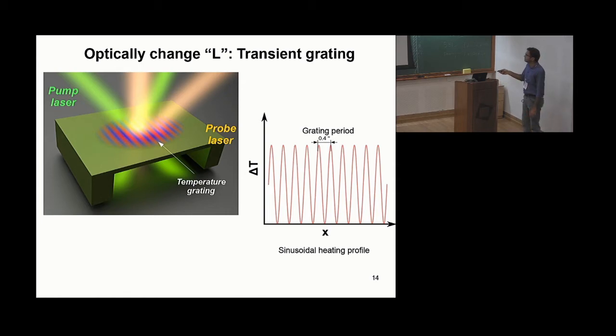So by simply tilting these green lasers to a larger angle, we can continuously tune the parameter L and measure the thermal conductivity of this material for each L.